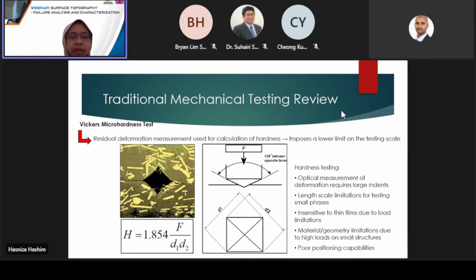First of all, let's look at the traditional methods of doing mechanical testing. When we want to get the hardness or modulus of a certain material, we normally tend to use the micro hardness testing. When we talk about the scale of testing, if we do the micro hardness test, we enter the micro regime of testing, but we still do not quite reach the nanoscale. As an example, this is a composite material that was tested using the Vickers micro hardness test, where the indent must be large enough to be inspected using the optical microscope. We can clearly see from these indentations that both the filler and base material were indented, or in other words, the bulk of the material was tested.